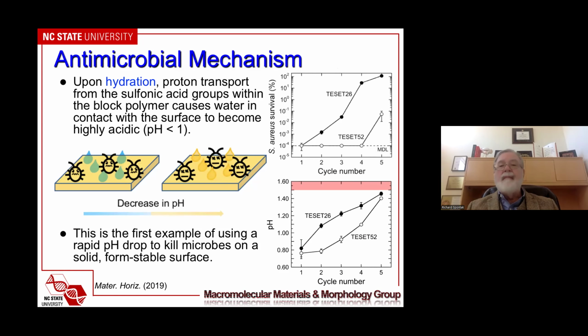How low? Well, what you see here, let's look at just cycle 1 for Staphylococcus aureus. Here's that 5-minute exposure and 6 log unit reduction. And you'll notice that the pH is about 0.8. That is significantly lower than your stomach acid. So this highly acidic environment is what causes almost immediate demise of the microbes that we tested.